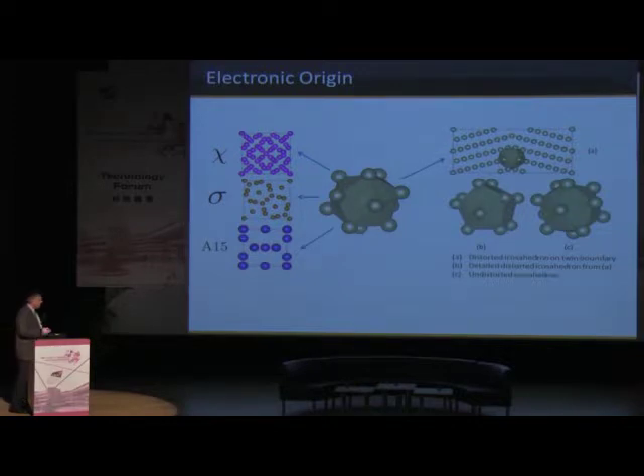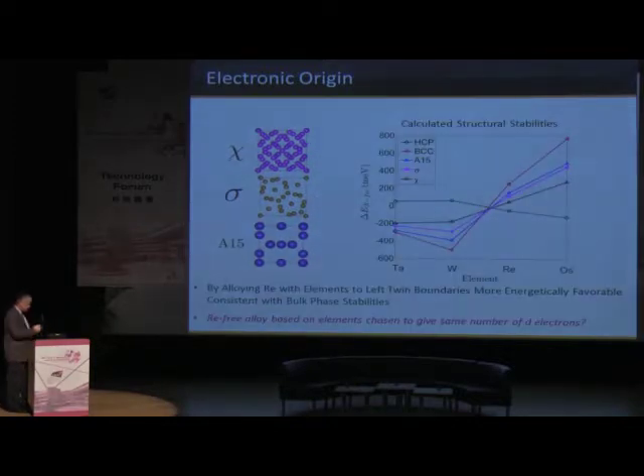Now, we understand from the calculation something very interesting. If you take these Frank-Kasper phases, which are the A15, the sigma, and the chi, and you look at their energy relative to HCP, so HCP is this line, and these are the transition metal series. What you find is that these icosahedral type structures end up having energy that's very, very close to HCP, and it gets even closer as we go over here between rhenium and tungsten.